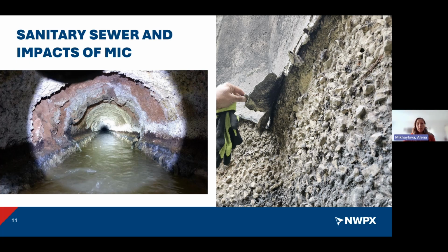And on the right-hand side, this was one of the lift stations. It's a square structure. It had previously been rehabilitated with epoxy coating. However, the epoxy coating kept failing. It was discovered that there had been a breach in the epoxy coating, and behind the epoxy coating, gases would get in and still eat up the concrete.